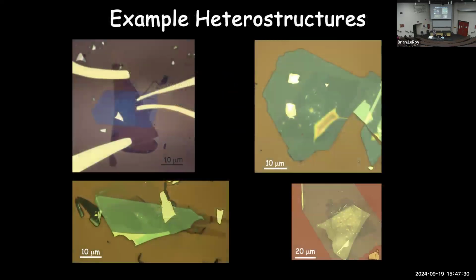And so here are some examples of what this looks like when we've done it. We've taken, in this case, different structures here. We have a blue one over here that's going to be something like tungsten selenide coming across here. We have pieces of graphite coming like this. You can't really see it in here, but there's another molybdenum selenide piece in here, and little graphite contacts to it, etc. Here you can see a boron nitride piece on the outside, a graphene piece along here. Here's one with a couple different layers. And so as I said, we have basically any arbitrary combinations that we can make by doing this stamping. We're just going to choose our types of materials depending on the physics that we're interested in studying.